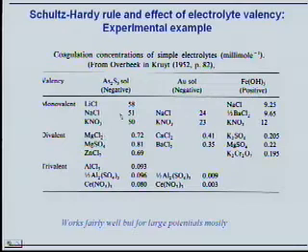These are data from literature. You have to add 50 to 58 millimoles of monovalent ions in order to precipitate some suspension of nanoparticles. Now, the sol actually is a suspension of nanoparticles. People didn't know that nanoparticles would be so fashionable one day, so they called them sols, but this is actually a nanoparticle suspension.